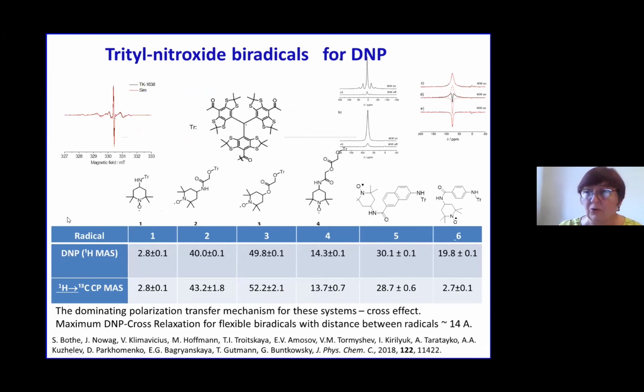And finally, I would like to say some words. I do not know about time, but I need 1 or 2 minutes to finish. Trityl-nitroxide biradicals for DNP. This work has been done in cooperation with Gerd Bunkowski. I suppose it will be continued. We also now cooperate with Songhi Han. What is interesting here, you know about DNP, that for DNP, especially in the solid state at low temperature, there should be 2 spins, at least nitroxide and trityl. So these biradicals were synthesized. You see that they have different bridges. I can't say that we got very exciting results, because the measured enhancement coefficients are not very impressive, but still they are quite large.